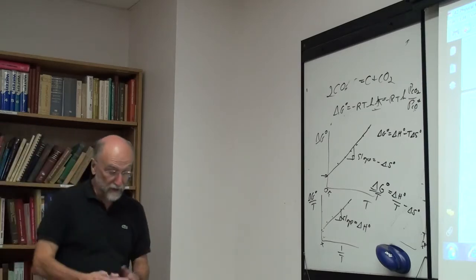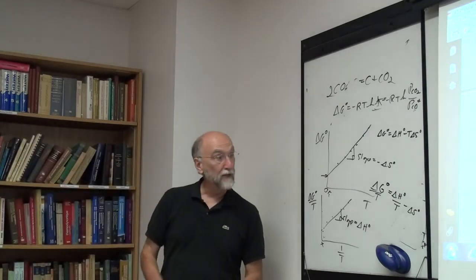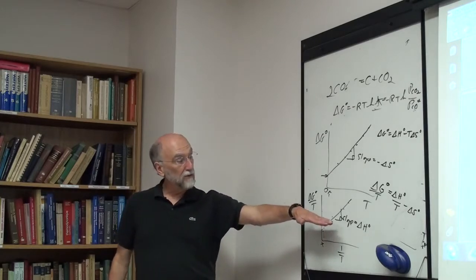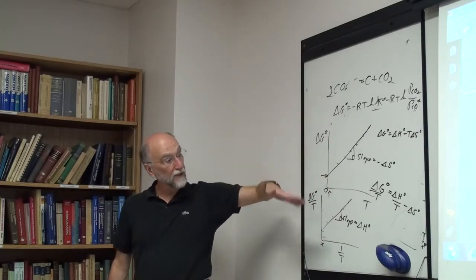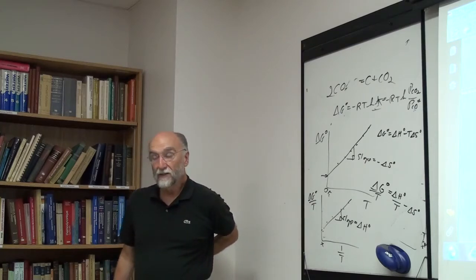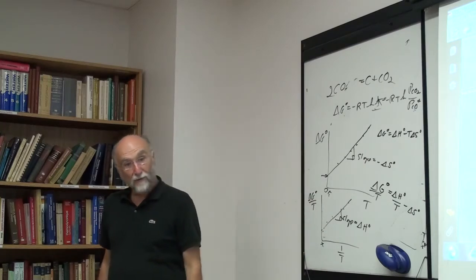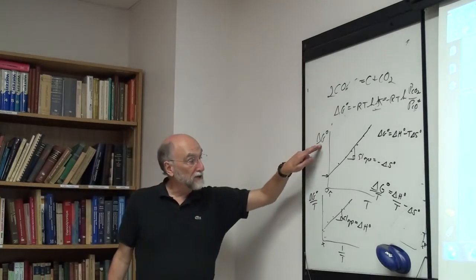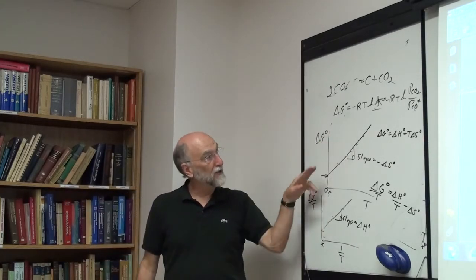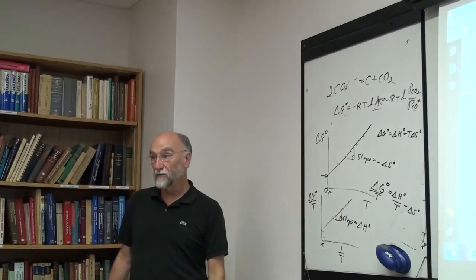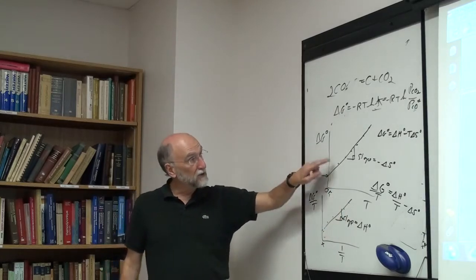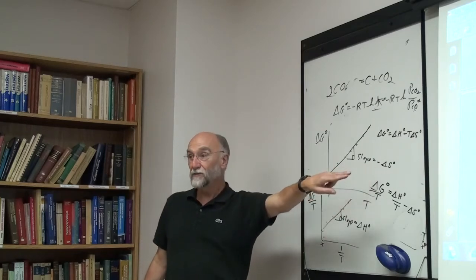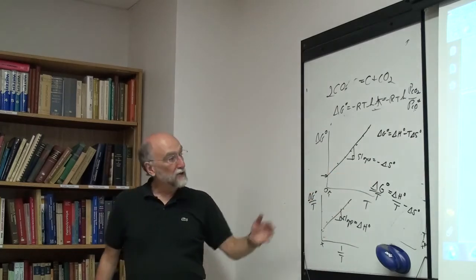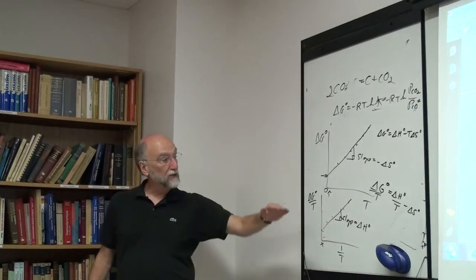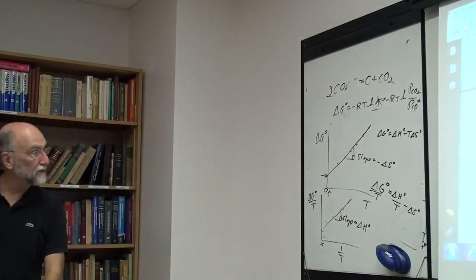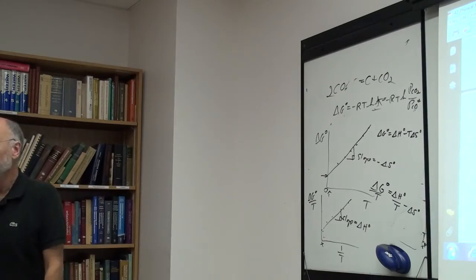In a calorimeter, you actually have to carry out the reaction from beginning to end and measure the heat. Here the reaction is not carried out, it's only systems equilibrated at different temperatures, and it gives you the heat for the reaction. This applies not just to reactions, it would apply to anything. If this was the Gibbs energy of mixing, then the slope of the Gibbs energy of mixing versus T is minus the entropy of mixing. If this is the Gibbs energy of fusion versus temperature, the slope is minus the entropy of fusion, and so on. Okay, this is another way of measuring the enthalpy. You can measure the enthalpy as the temperature dependence of the Gibbs energy without ever carrying out the reaction.